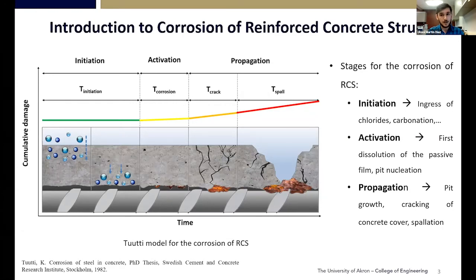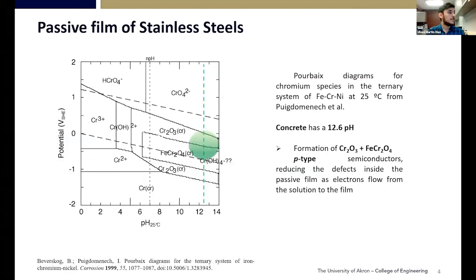So let's see now how this passive film is made and how we can see the protectiveness of our stainless steel. Concrete, as we've seen, has a pH around 12.6, and based on the Pourbaix diagram of iron, chromium, nickel elements at room temperature by Puigdomenech et al., we see the two main elements forming are the chromium oxide and the spinel phase, which both are p-type semiconductors, meaning that they tend to accept electrons, making the passive film less doped and increasing the corrosion protection.